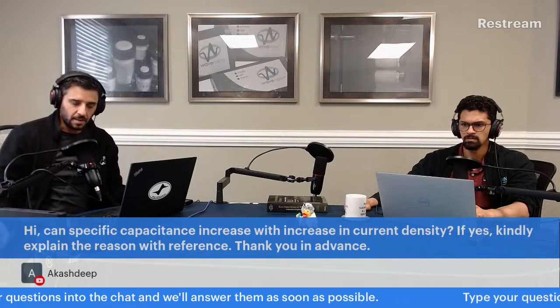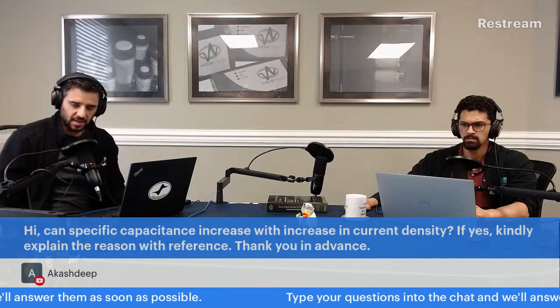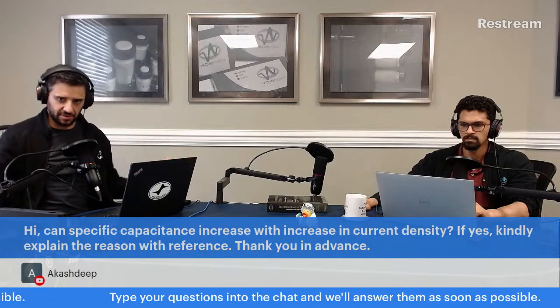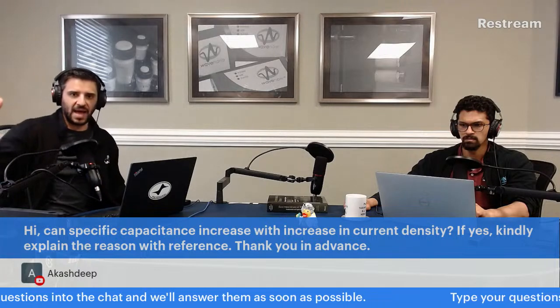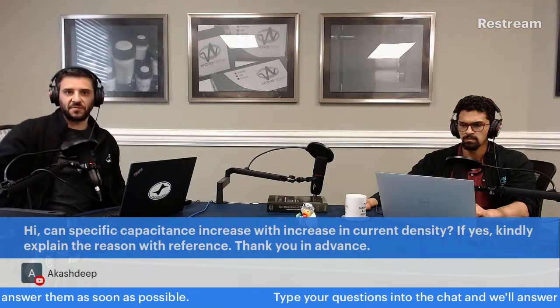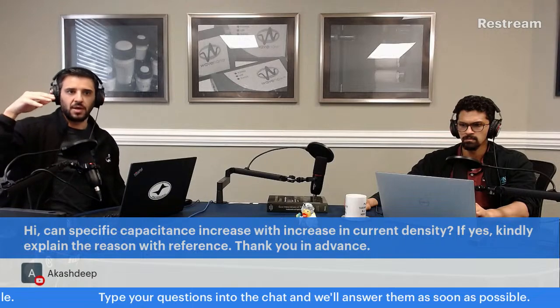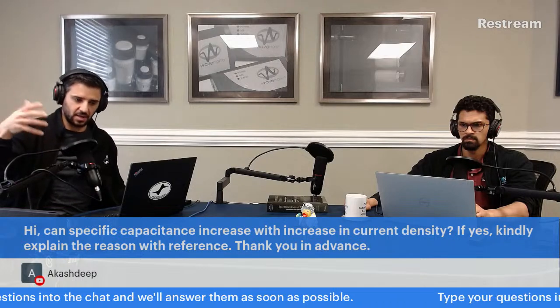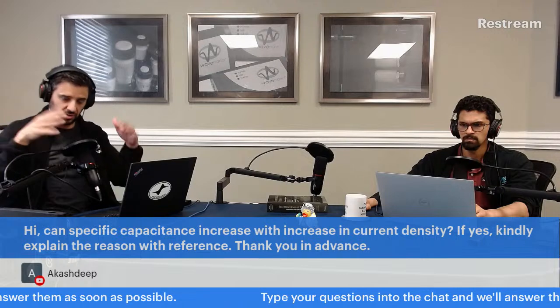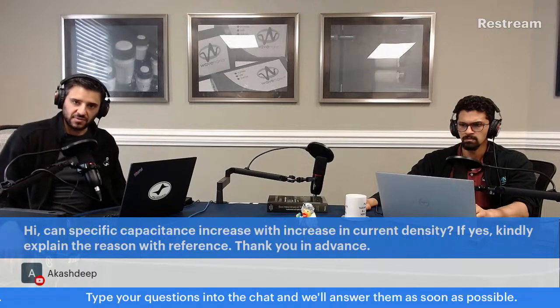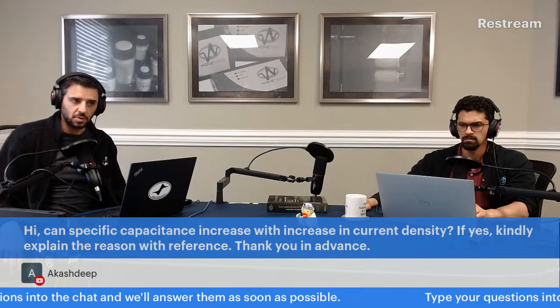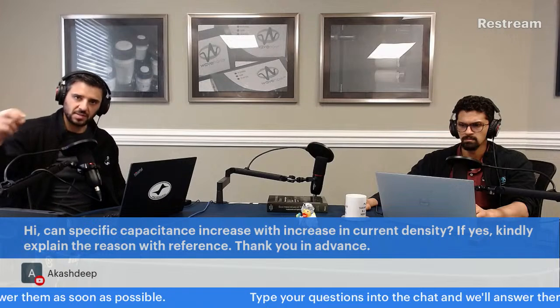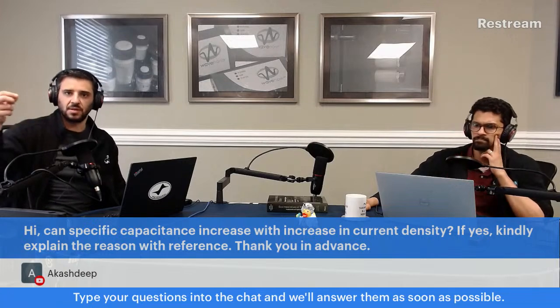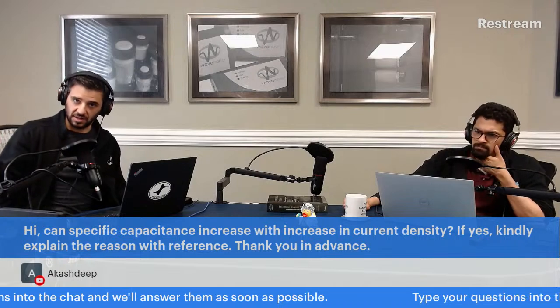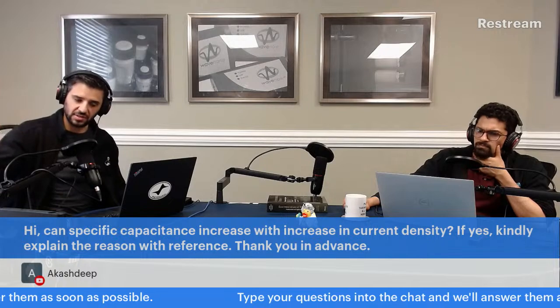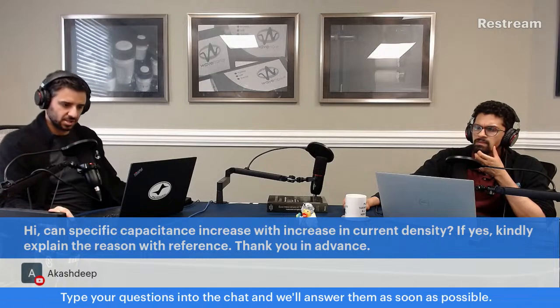Okay. So my guess is that would explain the phenomenon that you're seeing. Again, this is not always the case for every material in all situations, but in some situations, as the mass increases over some range, the surface area decreases because the material is no longer accessible everywhere, and it agglomerates. The particle sizes grow, the grain boundaries grow, and that decreases your effective surface area. And so this is why people try to, for academic purposes, decrease the loading sometimes, and decrease the size of the material, because you'll get more activity and more surface area. So I hope that's clear. I think that might be the explanation for what you're seeing.